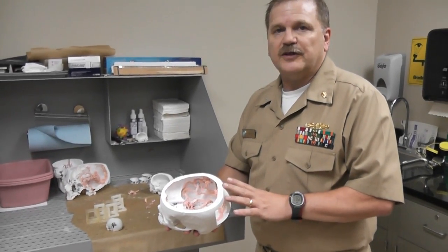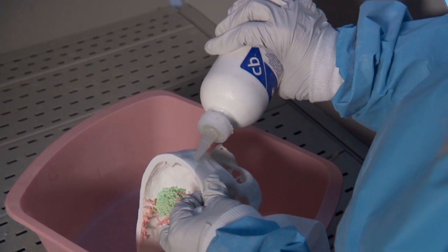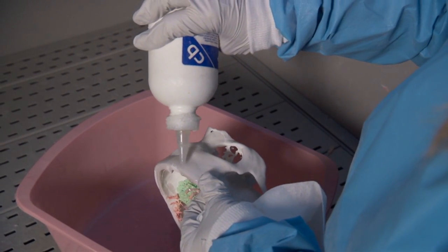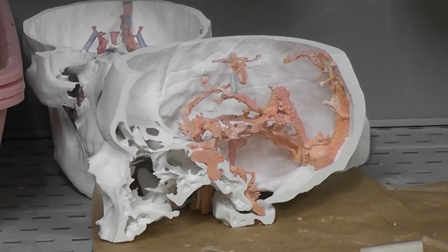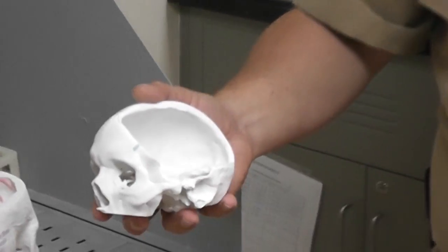So what you have to do is post-process it. We have two options. Generally you coat it in super glue, which makes it solid on the outside and relatively hard. Or you can pull resin through the whole thing. The nice thing about pulling resin through is that the models then cut like bone — and the beauty of that is what you would see in the bone is exactly what you see when you cut it.